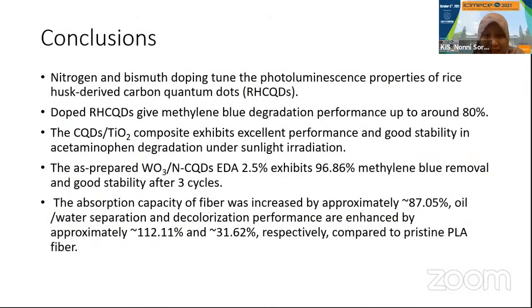But so far, what I can conclude about utilizing the carbon quantum dots, especially for the photocatalytic performance, right? Based on our result from doping, we can tune the photoluminescence properties of these carbon quantum dots. So we can modify it into a material that has blue shift or red shift, right? But the sole use of the carbon quantum dot itself does not really give a satisfying performance for the methylene blue degradation. We can reach up to 80% for the methylene blue degradation. So we think that for a more versatile application of these carbon quantum dots, we can combine it with other photocatalytic agents, such as titania. In the case of titania, when we combine these carbon quantum dots with titania, we can degrade the acetaminophen under sunlight irradiation.